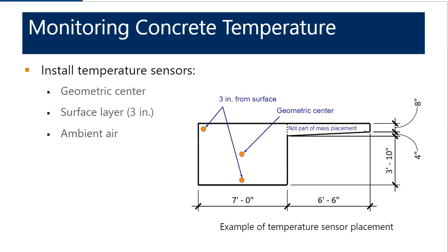And then you also install sensors near the surface at locations where you think the temperature gradients or temperature differences are going to be the largest. So in this particular example, I'm showing a sensor at a corner and at the base of the element, because those would just happen to be the particular locations for this placement where the temperature differences between the surface and the center were predicted to be the largest. We also recommend that temperature sensors are installed in ambient air to measure the ambient temperature and atmospheric conditions as far as validating the thermal model and also understanding what the risk is of thermal cracking if insulation were to be removed.